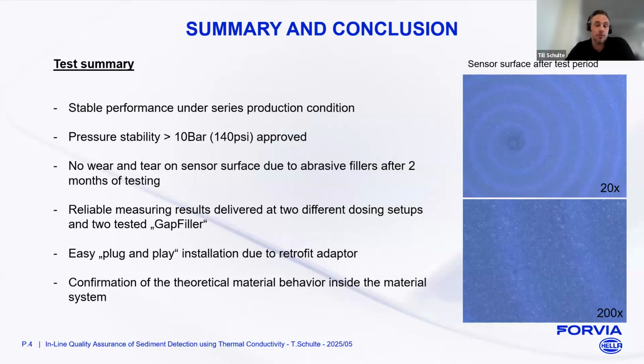We have no wear and tear on the sensor surfaces, as Brandon already said. On the right side, you can see the sensor surface after our testing period in different magnifications. The upper one is a 20-times magnification, and below you see a 200-times magnification, and there are really no scratches visible. We got reliable measuring results at 2 different dosing setups, meaning 2 different dosing speeds and flow speeds of the material through the sensor surface, as well as 2 different materials. We have an easy plug-and-play installation due to the retrofit adapter, and we got a confirmation of the theoretical material behavior inside the material system, because you couldn't look inside for sure.